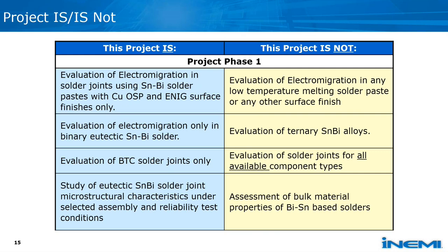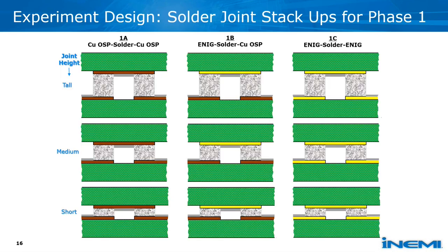Microstructural characteristics of the solder joint, again, pre and post electromigration, will be studied. This will also include the interfacial regions of the solder joint with the packages and board lands, where intermetallic compounds are usually formed. And these compounds have been known to impact the quality and reliability of the SMT joints. But the bulk solder joint characteristic will not be evaluated. Next slide.